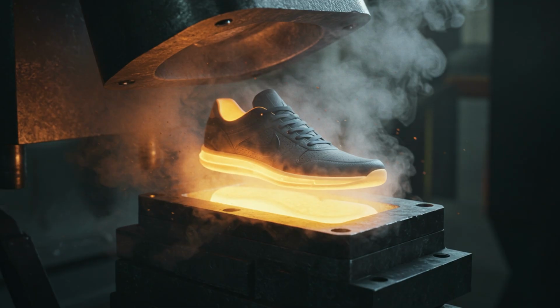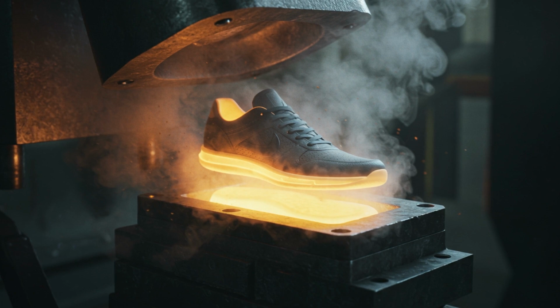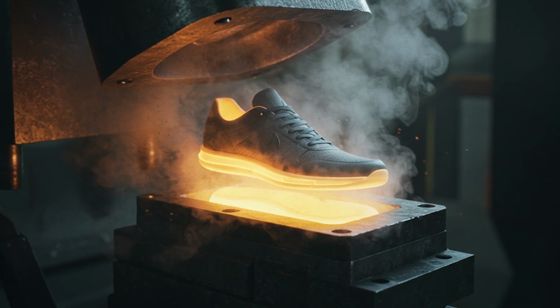It's like watching a marshmallow expand in a vacuum, but with violent speed. In an instant, the preform grows to its final size, increasing in volume by 200 to 300%. This is where the sneaker gets its soul. The expansion creates a closed cell structure, millions of tiny, independent bubbles that act as individual shock absorbers.